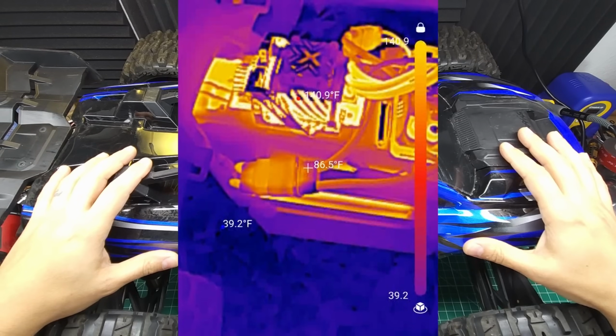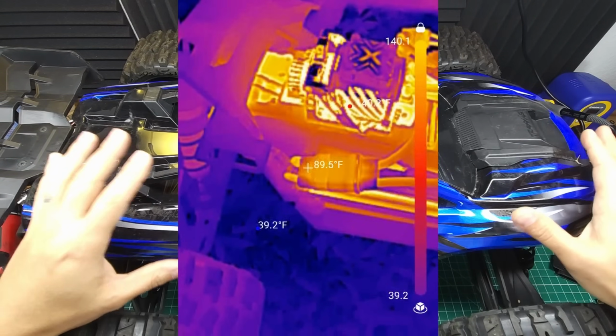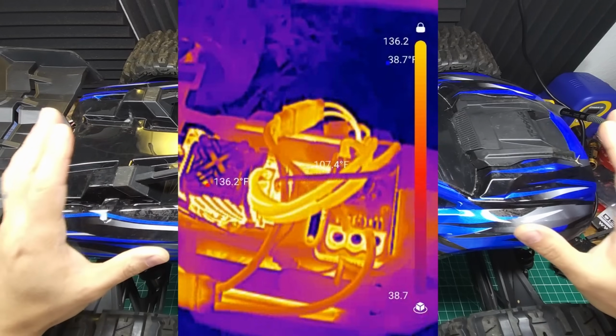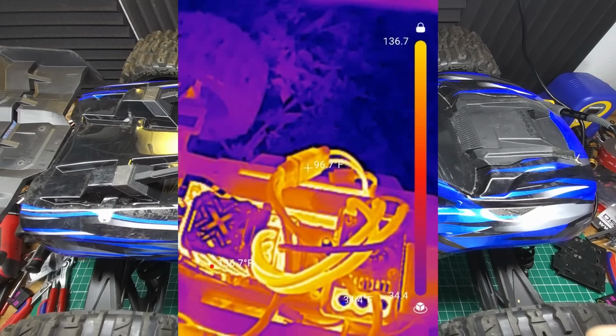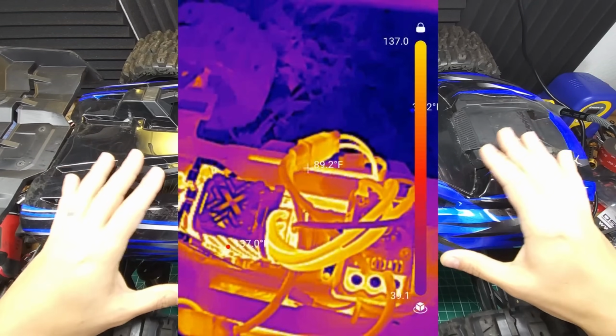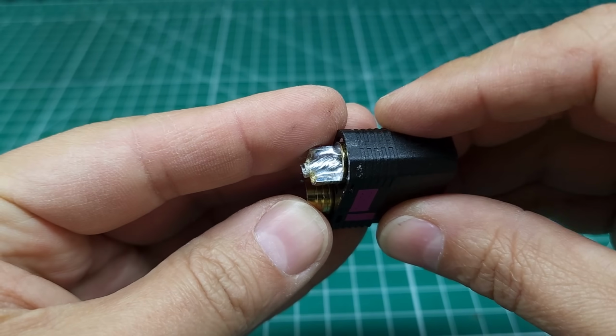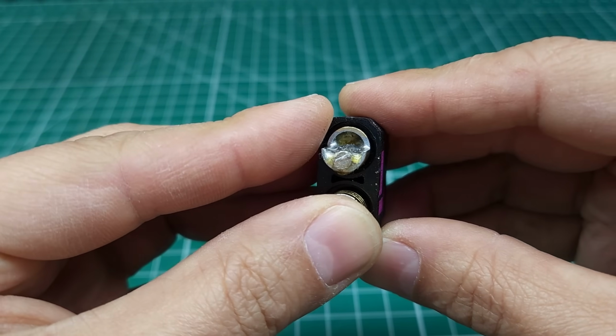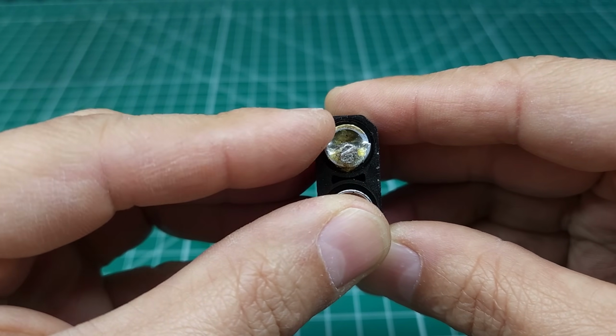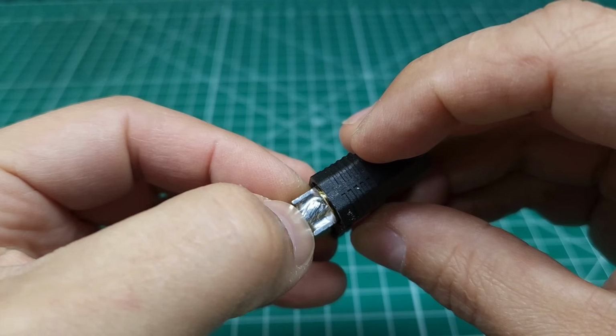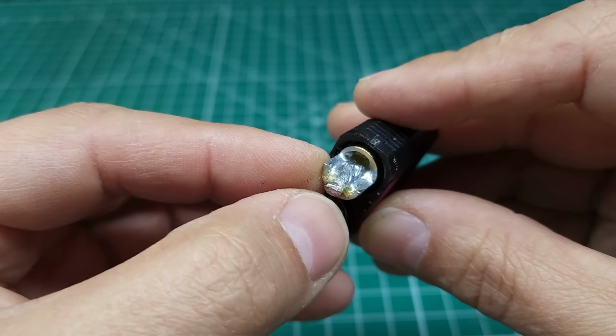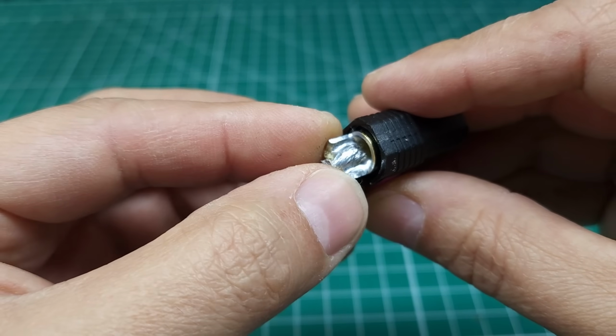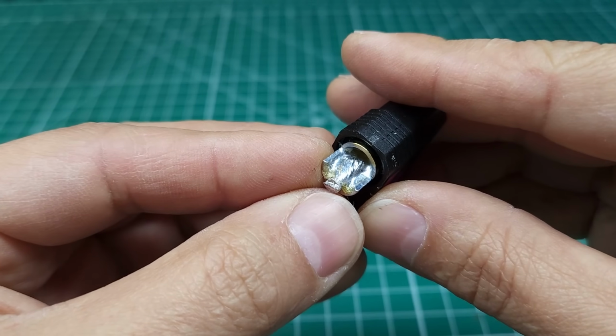As you can see here, the connectors themselves did get pretty warm, but on the ends where the solder joints are, it's actually cooler than it is in the middle. And in some places, the wires themselves are actually hotter than those solder joints are. And so ultimately, it seems like NASA has it right. As long as you have at least a 75% fill, which this is obviously way more than 75%, and the wires themselves are completely wetted and mostly covered, this joint is going to be just fine. And anything else you put on top of that's probably just going to be a waste.